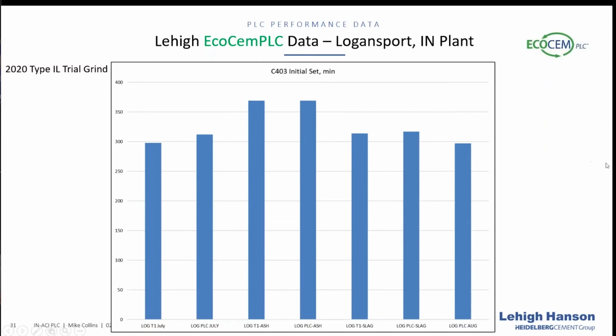So what about set time? Because all of us are interested in set time, so let's break those down like we did on our earlier chart. The very far left is the Logansport Type 1 from July. The Logansport PLC set just a hair longer, not very long, about 10 minutes longer. And then the August sample actually set equivalently to the July sample. So again, very similar performance and set time. When we looked at the fly ash, dead on. And this is doing C403 initial set with the penetrometer in our lab at Mitchell. And the slag mixes, again, almost dead on. So really, when we compare set time between equivalent SCMs or equivalent mixes, we're seeing equivalent performance.